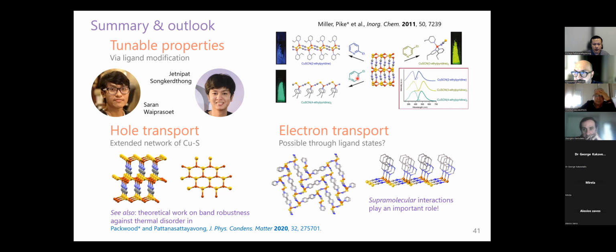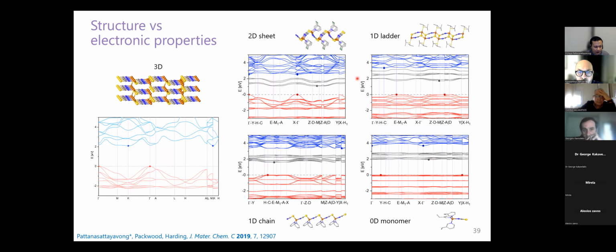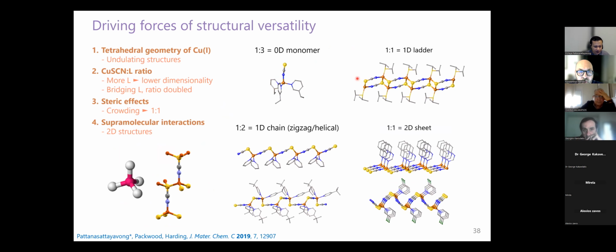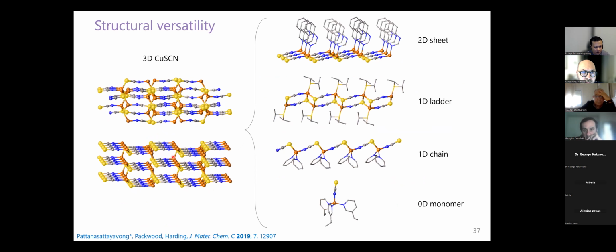These ligands, depending on the amount, if you add too much, the conductivity would be very low. And because I think in that paper he was looking at hydrogen sensing, the structure of the copper thiocyanate actually has enough space for hydrogen to go in anyway. Like this gap, for example, the pore within the structure. This is carbon, nitrogen, and also sulfur and copper. So these are quite big, and the hydrogens are quite small. So hydrogen can definitely go inside.